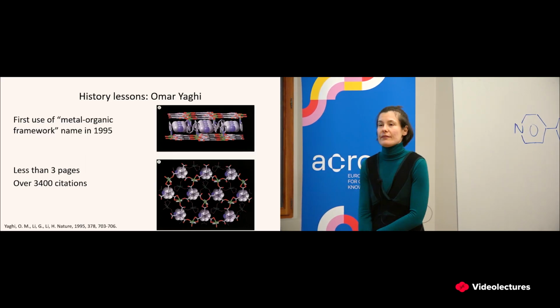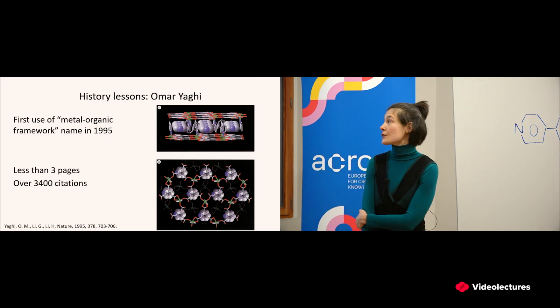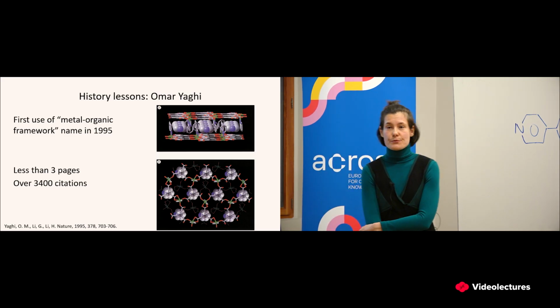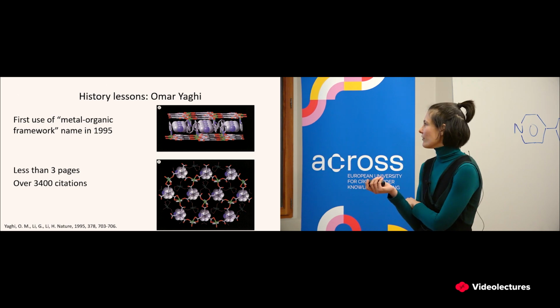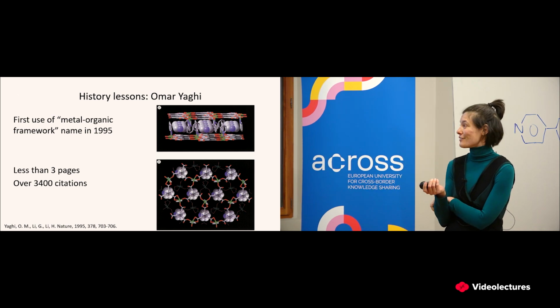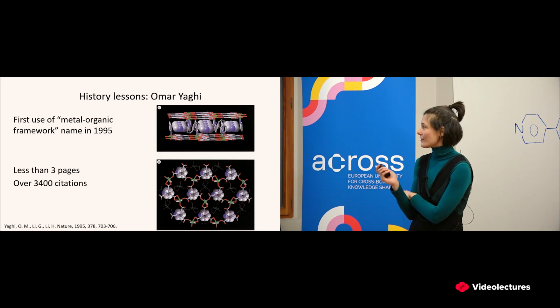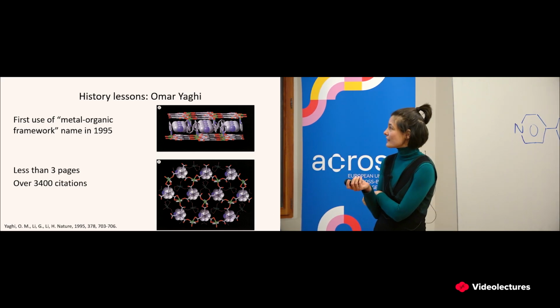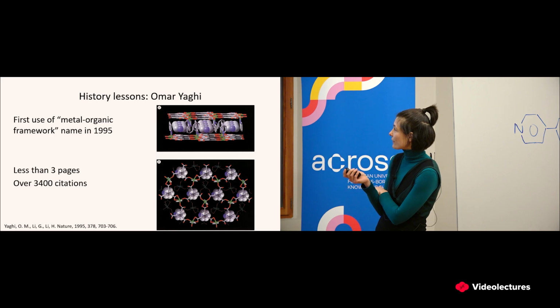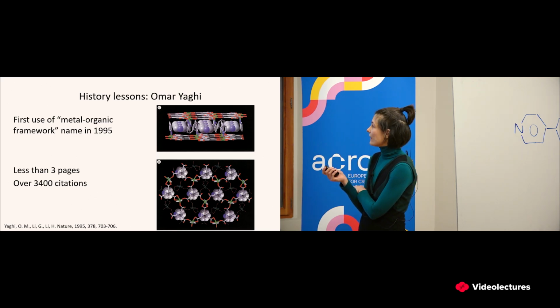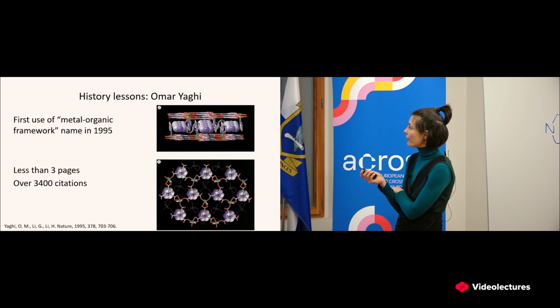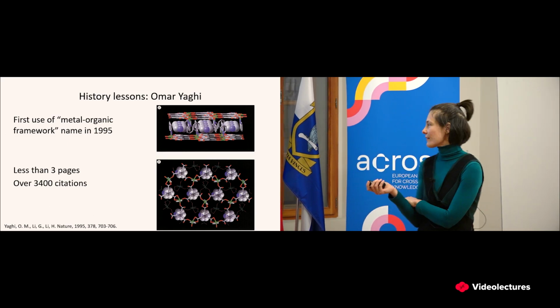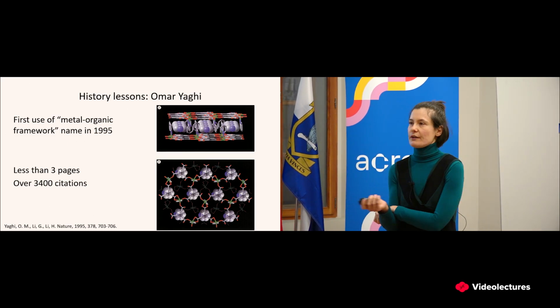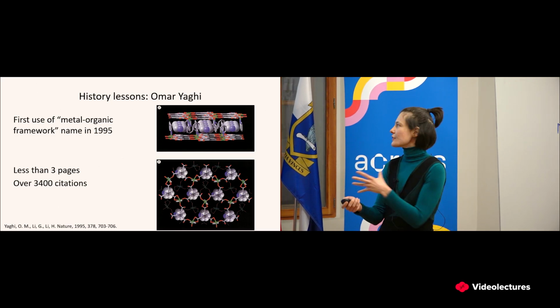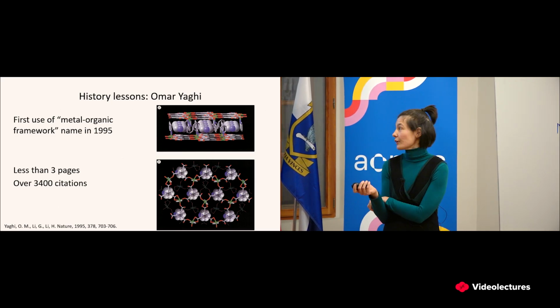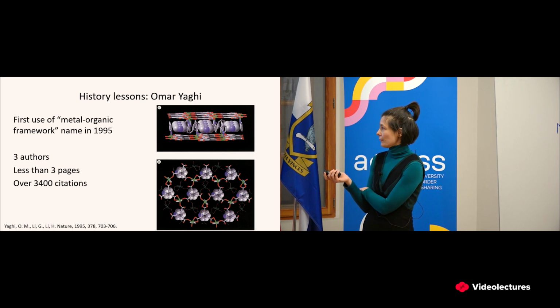So the first time that the term metal organic framework was used was actually in a publication published by Professor Omar Yaghi. This was a very short paper that was just 3 pages long, and by now has reached several thousand citations, and was published in 1995. So here you can see that between these layers, we have trapped molecules of pyridine, which in this case acts as a guest, right? So this is the molecule that we can reversibly capture in between the layers of this metal organic framework.